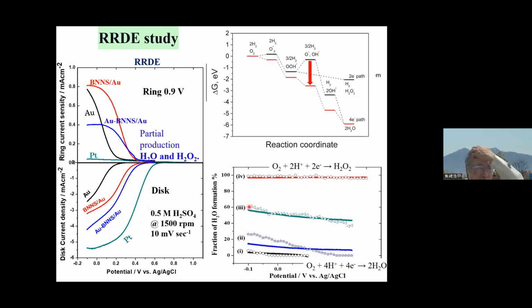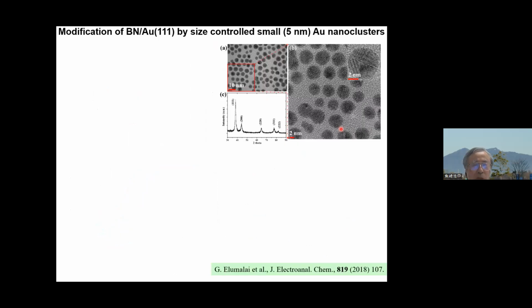Okay. So then, of course, we need to know why. We again calculated the free energy diagram utilizing the small gold nanocluster on top of boron nitride. It showed that this step, which inhibits the whole 4-electron reduction, is stabilized quite well. So the small gold nanocluster stabilizes this step, so that the 4-electron process is started. So if that is the case, then it is better to have a small gold nanocluster.